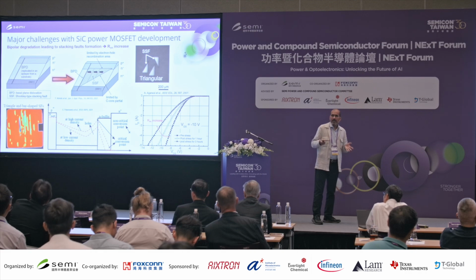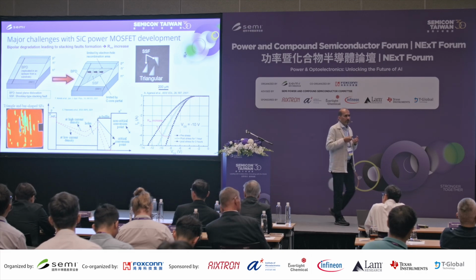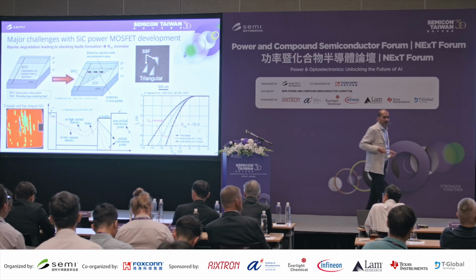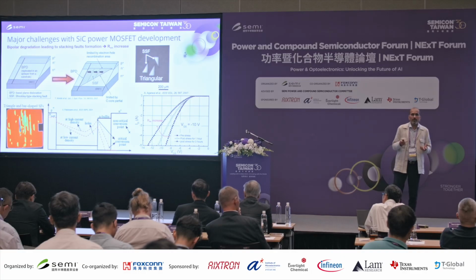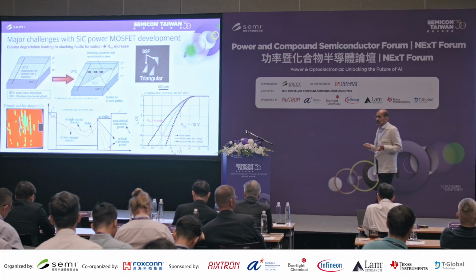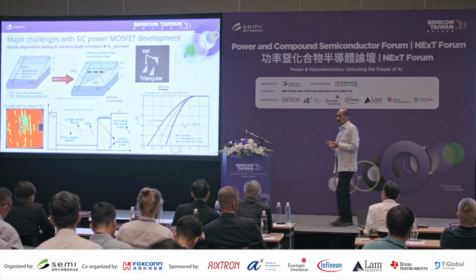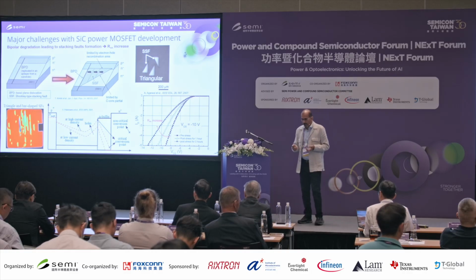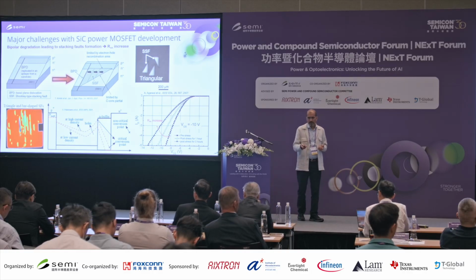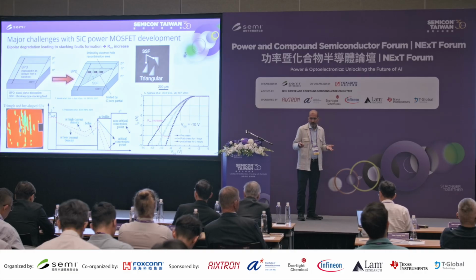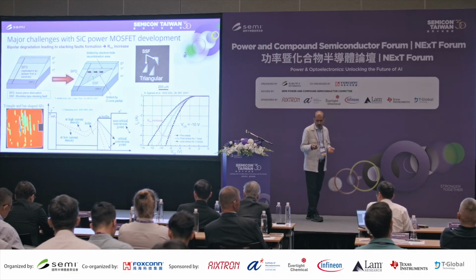For that, one has to have a lot of know-how in how to start the epitaxy growth, to convert these BPDs coming from the substrate to TEDs. And that conversion has a lot of tricks. Otherwise, you can see on the bottom left the graph showing that after stressing, there is a lot of stacking fault generation.